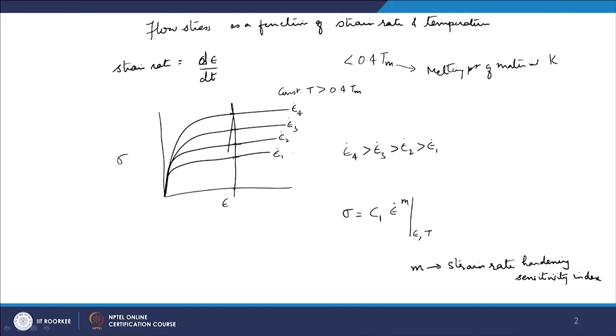So, the strain rate hardening is a very important parameter, which stabilizes the deformation or which gives a uniform deformation. So, material experiences strain rate hardening, and how to find out this strain rate sensitivity index, again we can do a similar thing to what we did earlier. If I take logarithm on both sides, it will become something like this: ln sigma = ln C1 + m ln epsilon dot. C1 is some material parameter. So, basically if I plot ln of epsilon dot versus ln of sigma, the slope should give me the strain rate sensitivity index.